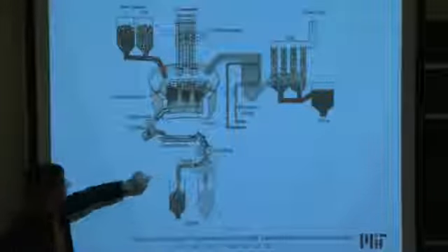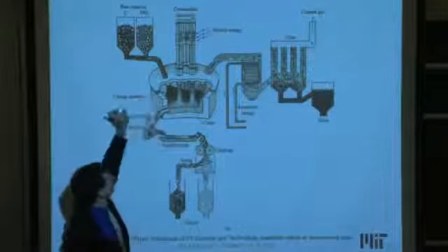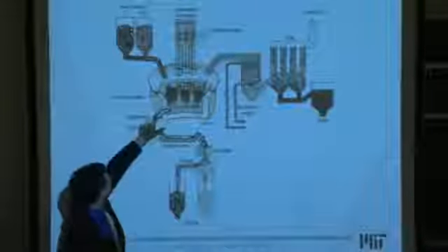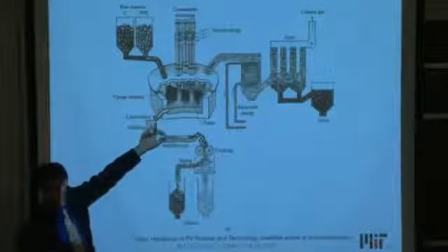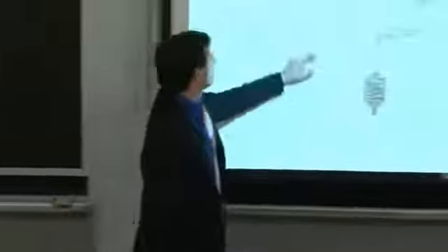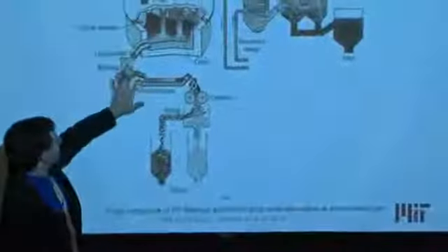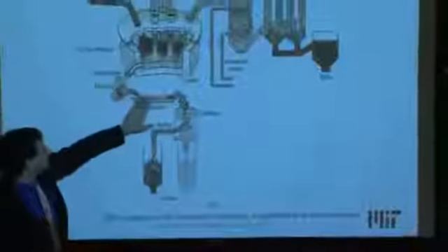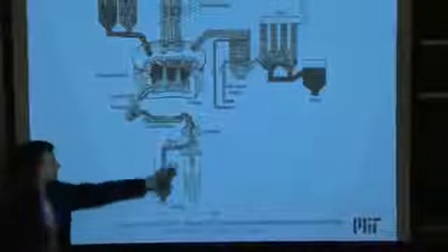Flag that. Put an asterisk next to it. We'll come back to that in a sec. Other byproducts of this reaction. So this is the liquid silicon metal coming out here at the bottom. It's essentially liquid molten silicon. Reduced, so silicon 0, not a silicon oxide. Reduced silicon metal. And then finally, it's poured into these buckets, also called ladles, and solidified, crushed up to size, and then distributed at the end.